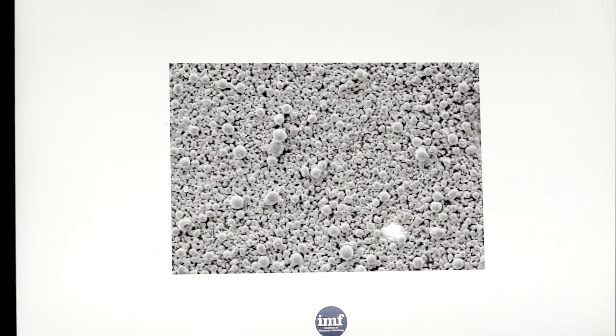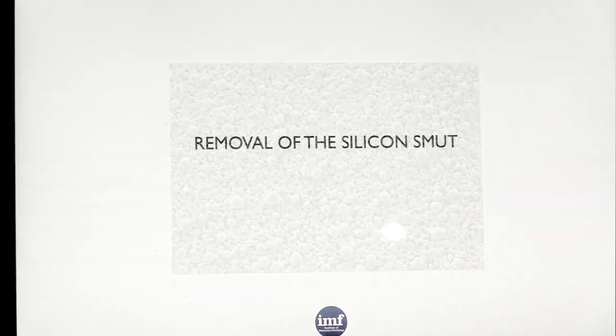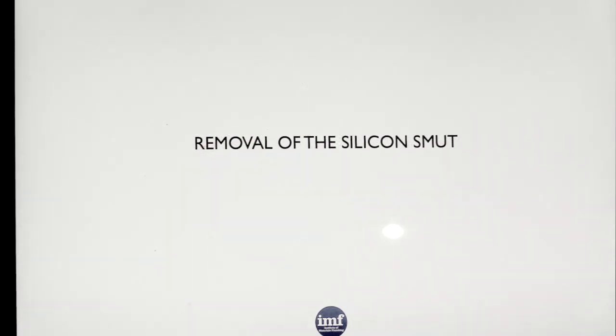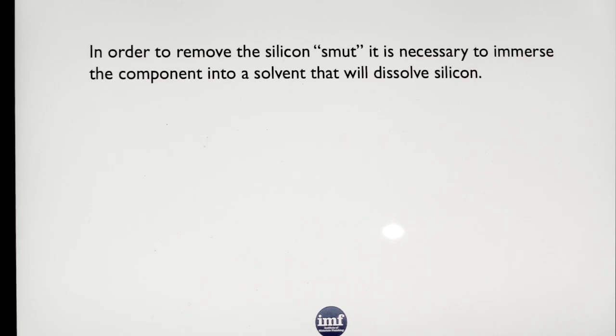These large lumps here are the silica. This underneath is the actual aluminium etched coating. That has been slightly exaggerated, obviously for the purpose of showing you the photograph, but in real terms, that's what it looks like. And if you don't do anything about it, these lumps will just get magnified up in electroplating. So we've got to remove that silicon smut, okay? So you need something that will dissolve silicon,